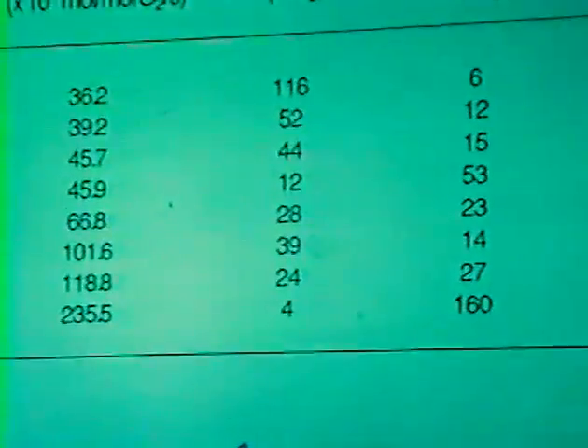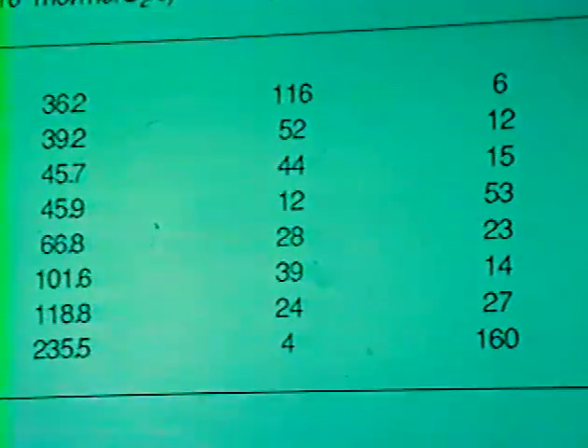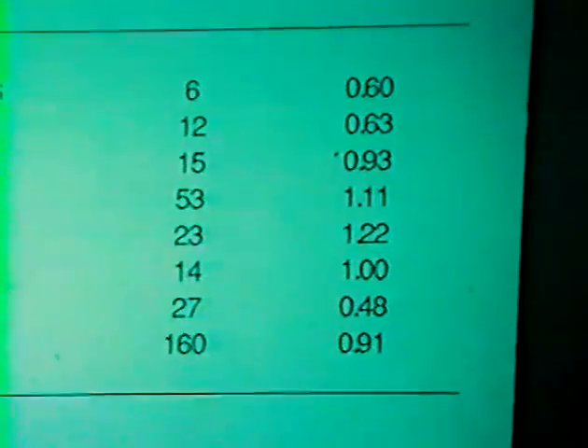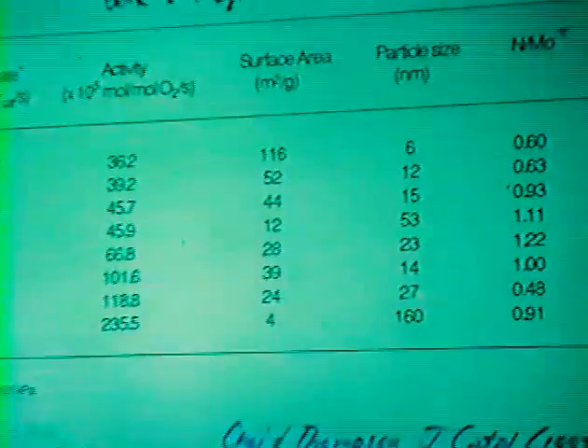As I mentioned, we also need to be aware of what the nitrogen to moly ratio is. You'll notice that there is not a clear correlation between nitrogen to moly ratio and the catalytic activity. One note that we should make is that for the samples with the larger particle sizes, it appears that nitrogen to moly ratios near 1 produce the higher activity materials. And as I'll show you in a few minutes, we believe that's because of the presence of the delta phase near the surface.